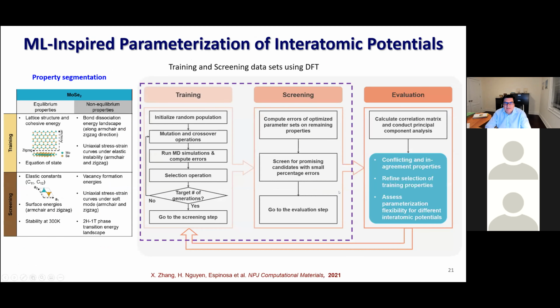So we propose a different way that, for us, was inspired by many of the machine learning strategies and algorithms, which is, again, you obtain training and screening data sets with the density functional theory. But we did two major things here. One is because we're interested in fracture. Fracture happens with deformations and atomic environments that are far from equilibrium, far from minimization of the energy. And so we took equilibrium properties, but also non-equilibrium properties like bond dissociation, energy landscapes, large deformation stress strain curves, phase transitions.